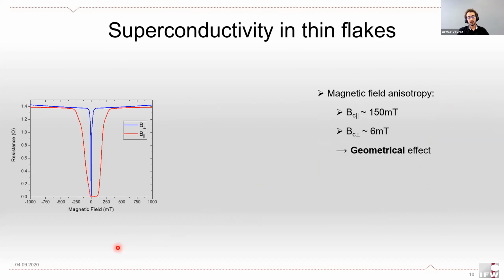When we applied a magnetic field to our sample, the first thing we noticed was that we have a very different response whether we apply a perpendicular field in blue or a planar field in red, with a much lower critical field when the field is perpendicular to the sample. This is actually understandable simply as a geometrical effect, since our sample is much wider than it is thick.